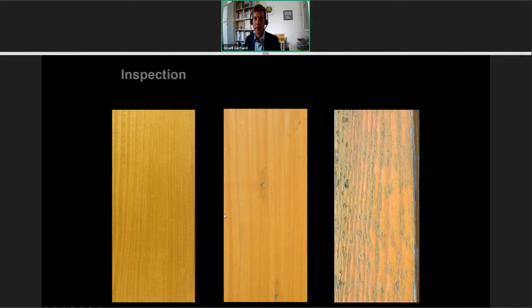And this should illustrate that in this stage, the coating needs regular inspection in some intervals. Some say every year you should take a look at your coated surface. And if you do that and you find defects early enough to repair them by maintenance, then you have really gained durability of exterior wood. So inspection in regular intervals, as long as the coating is intact.